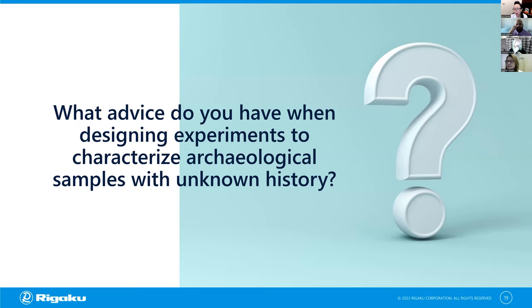And it was one of the, I think, images that Chandra had shared on one of her slides. First question. For the 0.5 centimeter field of view scan that you did, Chandra, with 10 micron resolution, do you recall what energy, voltage, power you might have used on your settings? 130 kV, yeah.